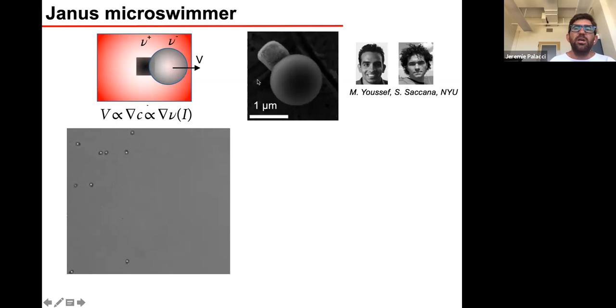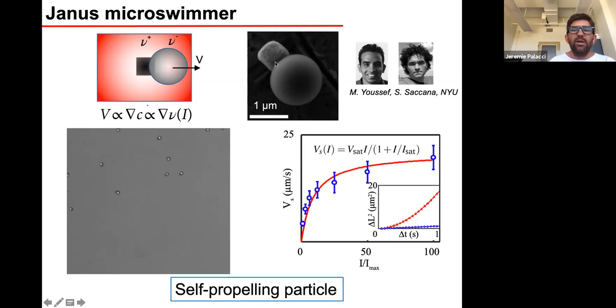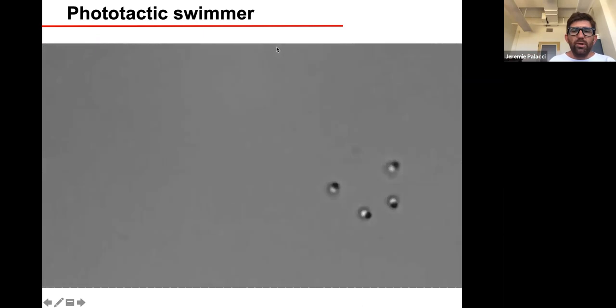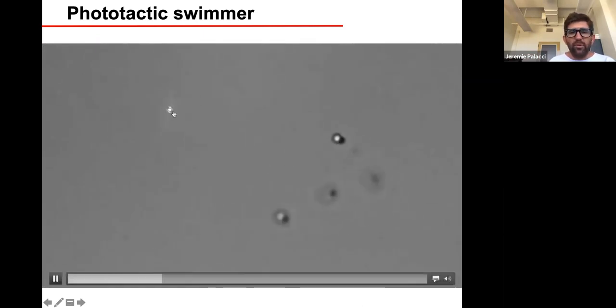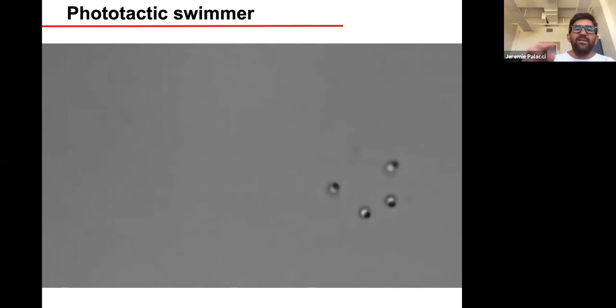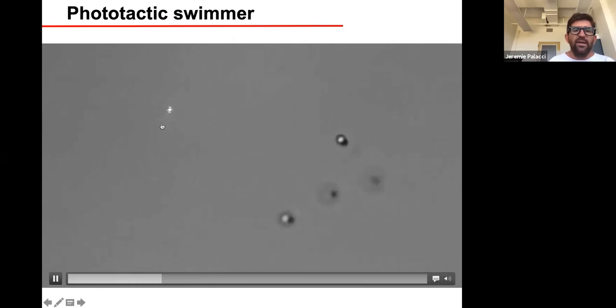It's just like a variation of the particle I showed you before, where basically the cube is more extruded than previously. So why do we extrude the cube? I'm going to show you in one second what happens if we take those particles and put a gradient. So we put a laser here, so we have a light gradient. What we see is that the particles, which originally were inactivated, so there was just Brownian motion, all start migrating towards the bright spot, which is a laser spot. Now it seems that they're not moving, but we're actually moving the stage. So if they can stay near the laser, it's because they can continuously migrate to recapture the light spot while the stage is moving. So basically we have a particle which is phototactic.